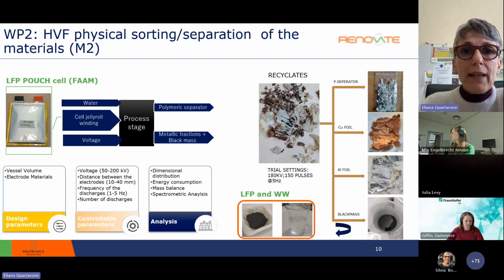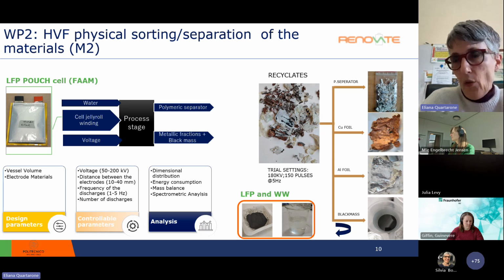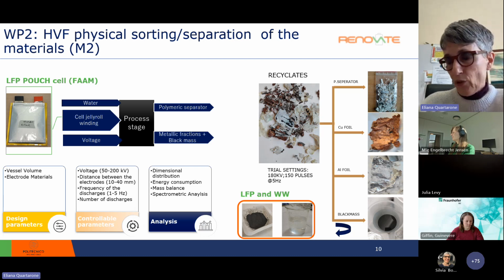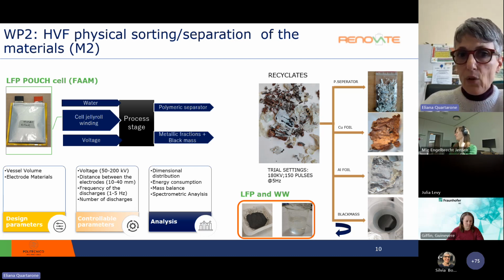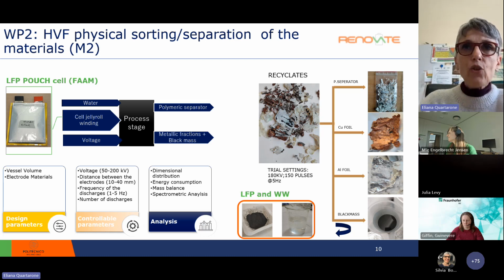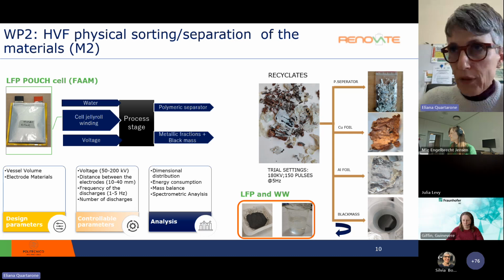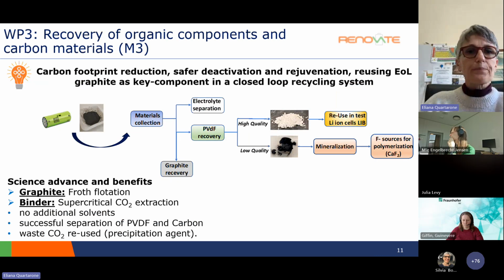And what you can see there is the separation that, of course, we still need to further optimize. The plastic separators of the cells, the current collectors, and the concentration of black mass made by LFP and graphite dispersed in the wastewater here. And we are now at the level of characterizing each fraction in order to also modulate the parameters on which the high voltage fragmentation is based.